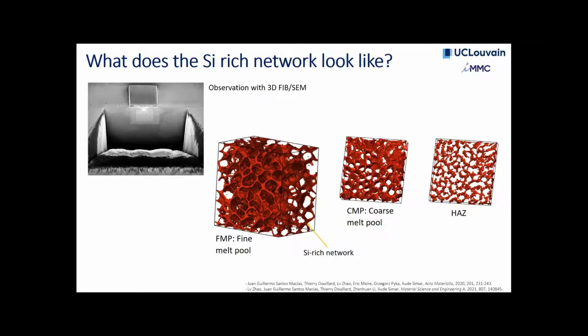So here, just to show you what this silicon-rich network looks like. We did some FIB-SEM with Thierry Douillard in Lyon. And here is what the microstructure looks like. So this is a very nice image of this very connected silicon-rich network. And here is what it looks like in the melt pool and the heat-affected zone. And as you can see here, there is a difference in connectivity in these three regions of the as-built material.